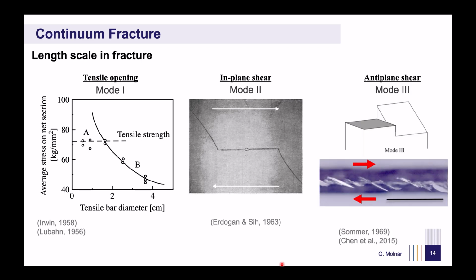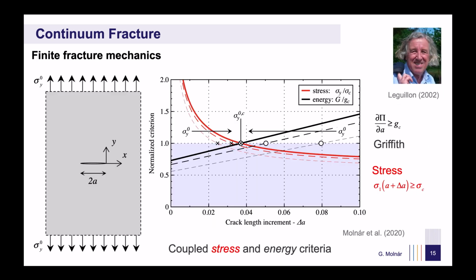Finally, in anti-plane shear, I will show how the primary crack breaks into smaller facets, daughter cracks, which then merge to follow the loading direction. In all 3 cases, we will see how regularization enables insights that are not possible using traditional linear elastic fracture mechanics. However, since phase field simulations do not always explain why certain phenomena occur, we will use the coupled criterion to better understand these numerical results.